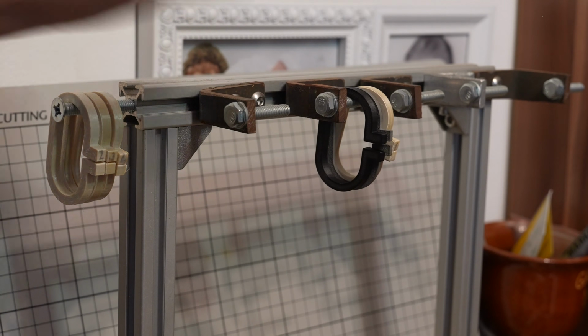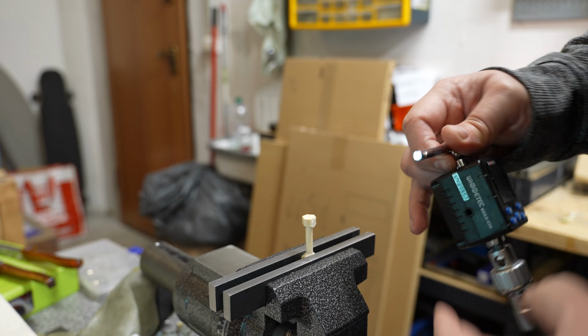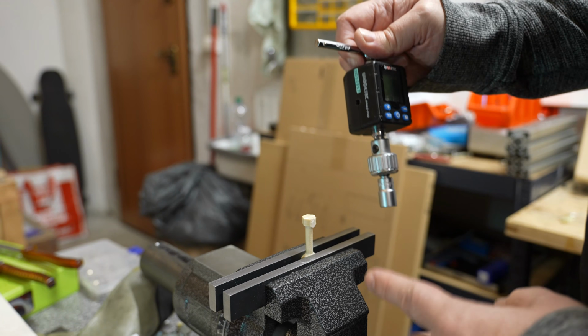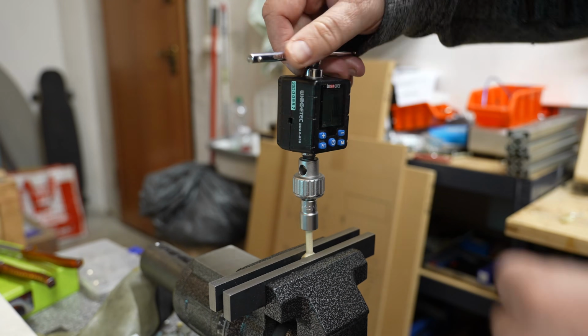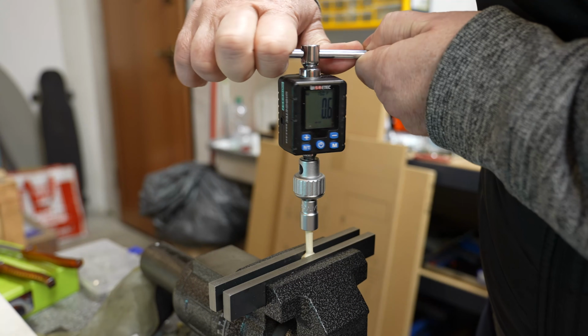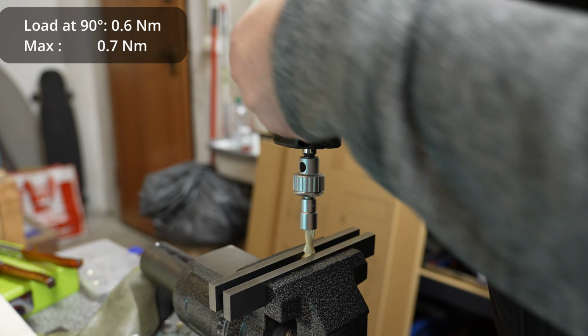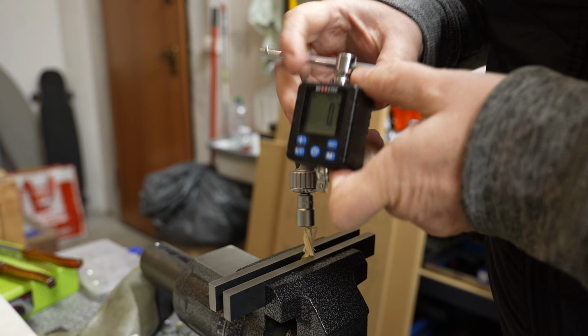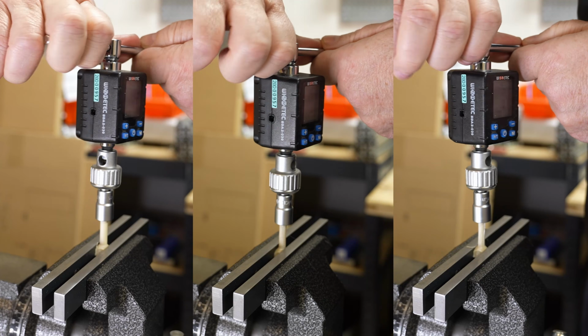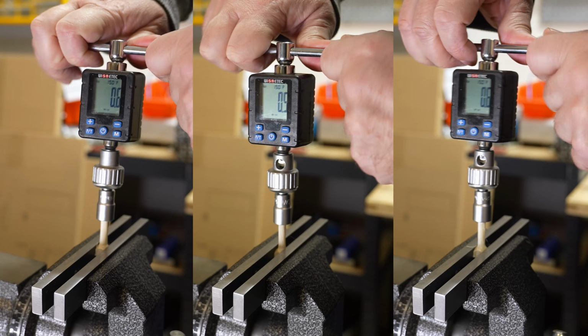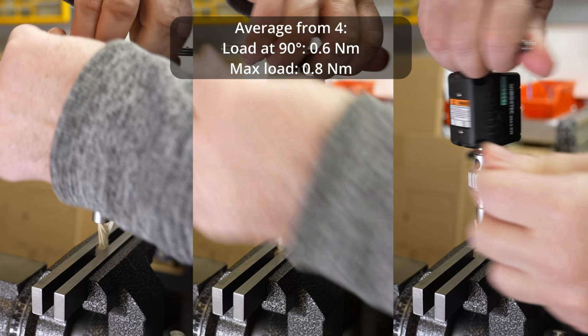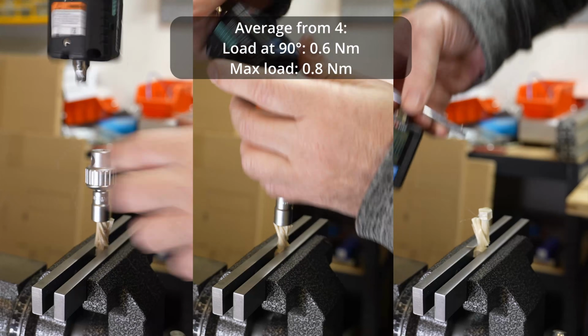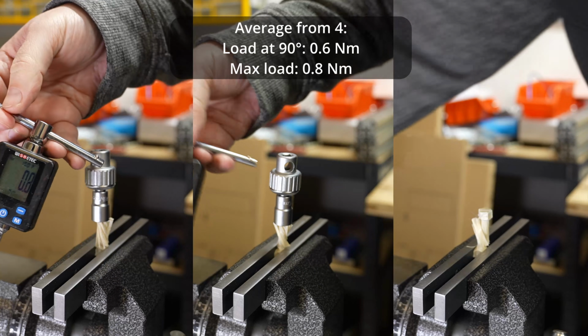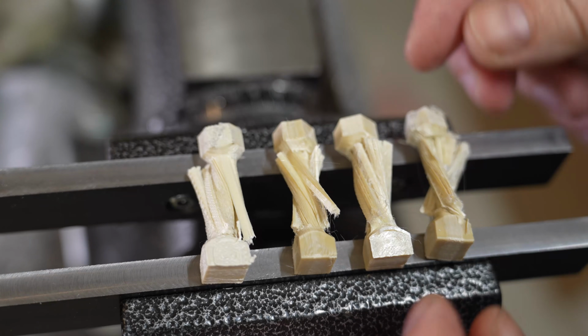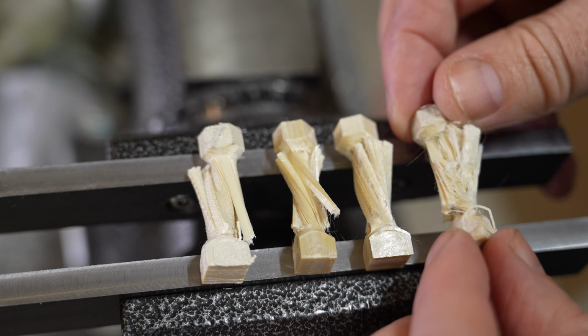It's a good start, but let's continue with the testing. The torque or twist test and these test objects are printed in a horizontal position. 0.7 the peak. Similar results I got with the rest of the test objects. Big average load at 90 degree rotation 0.6 Nm and the maximum 0.8. It just doesn't have a chance to be strong in this test because of that weaker layer adhesion.